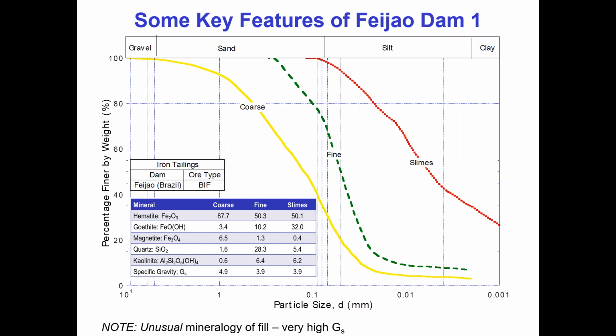The slime material in the Feijao Dam to the far right has a clay content somewhere in excess of 50%. I should say that this is very low plasticity fines. But before we go further, you'll see the coarse material may have as little as perhaps 10 or 20% silt fraction and is likely to be free draining. And when you put more and more fines in there, you will reduce the permeability. You may also have some influence on the shear strength, and that's the fines material.